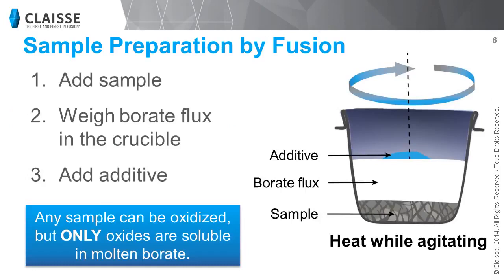Sample preparation by fusion is a very simple technique. If you want to do a borate fusion, you must weigh your sample in the 95% platinum, 5% gold crucible, in which you also add the borate flux. The borate flux can be lithium borate, lithium metaborate, or a mixture of both. Also, you might need to add an additive such as a non-wetting agent or an oxidizer.